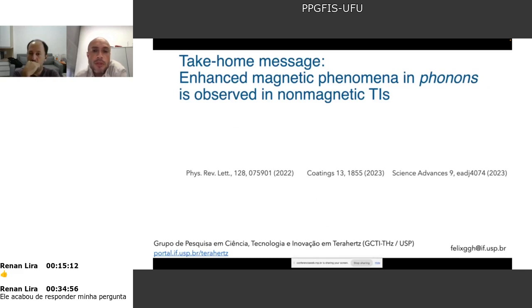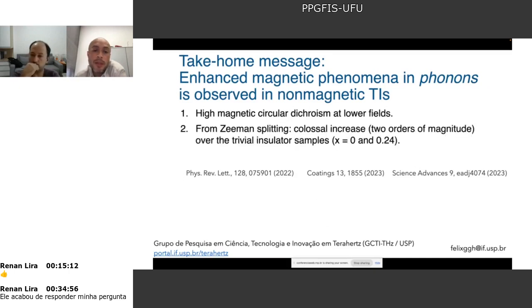Okay, so I want to finish with this idea then that there is enhanced magnetic phenomena in phonons for non-magnetic TIs. If you want to see more details, you can look at these three publications. There is a lot of theory in those papers. I only focus on the experimental part in my talk. We saw high magnetic circular dichroism at lower fields for TCIs, a colossal increase of 2 orders of magnitude over trivial insulator samples, and we also see an increase of 1 order of magnitude in the diamagnetic shift.